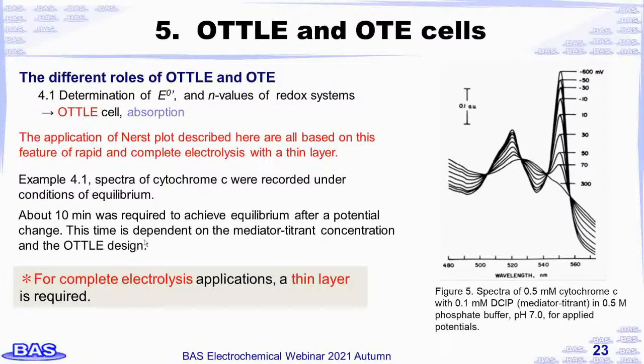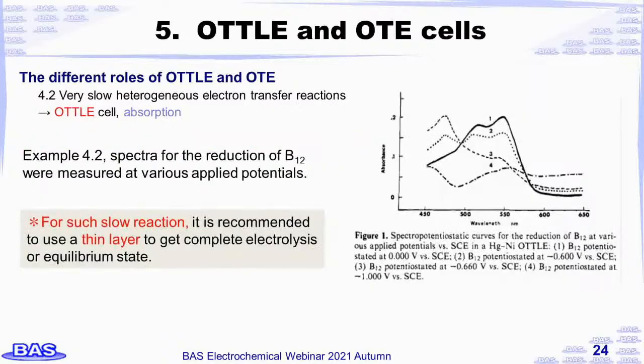About 10 minutes were required to achieve equilibrium after a potential change. This time is dependent on the mediator titrant concentration and the OTTLE design. Therefore, for complete electrolysis applications, a thin layer is required. Example 4.2. Spectra for the reduction of vitamin B12 were measured at various applied potentials. For such a slow reaction, it's recommended to use a thin layer to get complete electrolysis or an equilibrium state.